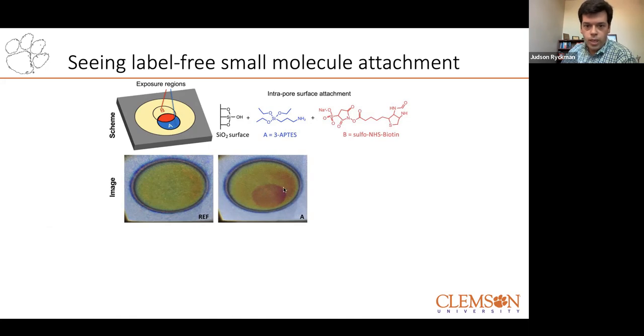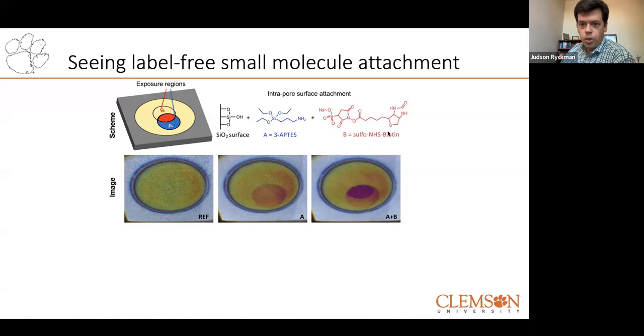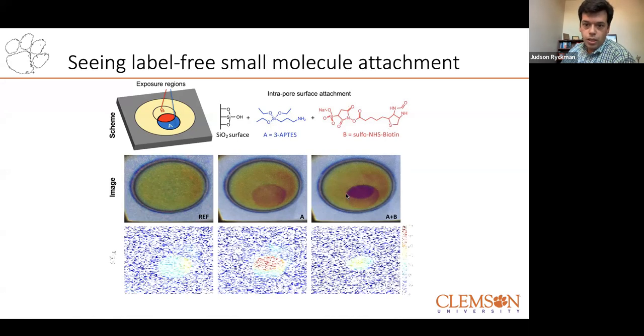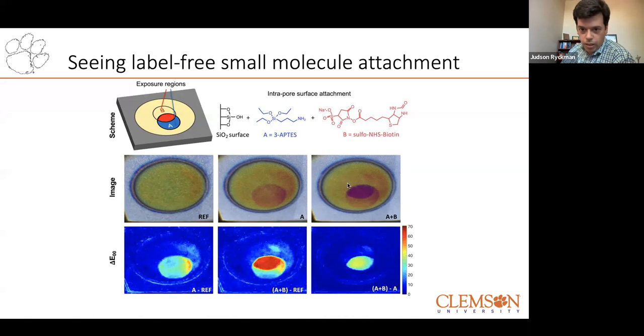So here's our aminosilane. We can see it's changed the color of the sample. It's increased the refractive index, and as we've measured also the optical properties of the sample, we're relatively confident that we haven't done a really poor multi-layer, but it's a pretty well behaved monolayer. Come in with our sulfo NHS biotin, and we see that specific binding where we only put down the sulfo NHS biotin where there's an amine terminated surface. You do see a little bit of non-specific interaction. There's a light color change here, and we can do more sophisticated image processing on this type of sample to really measure what's going on. But you can see we've transduced the presence of a thin monolayer of molecules, which you might otherwise need, say, an ellipsometer to do. And now you can see it by the naked eye or a smartphone camera.